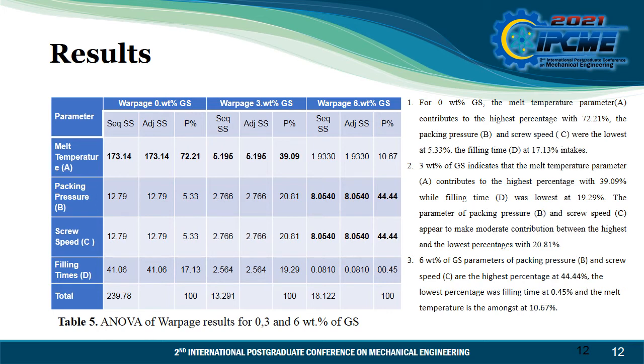This is the result for warpage. For 0% natural fiber, the melt temperature has the highest percentage contribution, which is 72.21%. The lowest is 5.33%, and the next is filling time at 17.13%. For the 3% Gigantochloa Scortechinii fiber, it is indicated that the melt temperature parameter A contributes the highest percentage, which is 39.09%, while the filling time was the lowest at 19.29%.